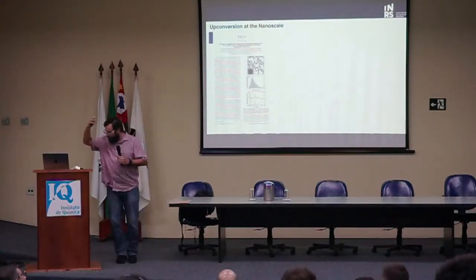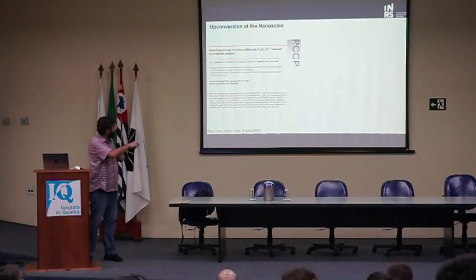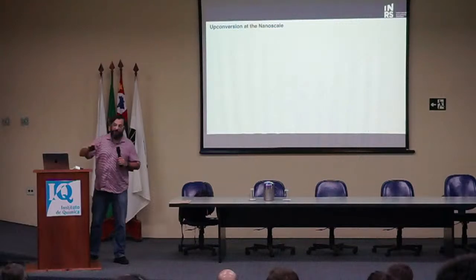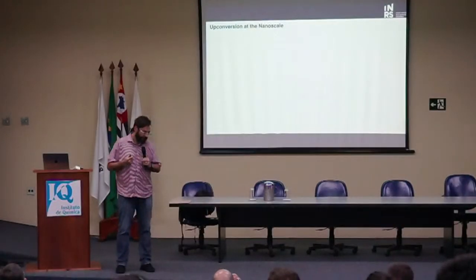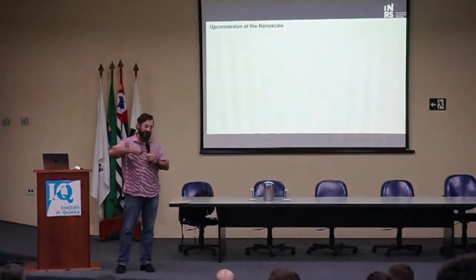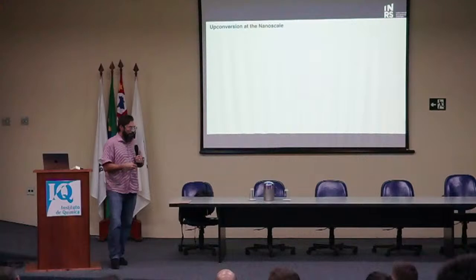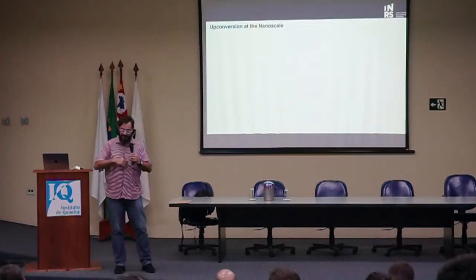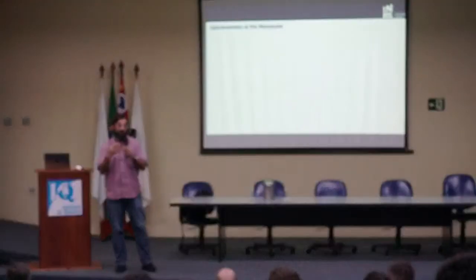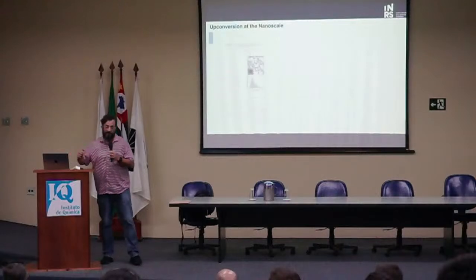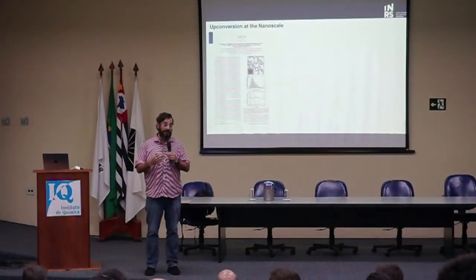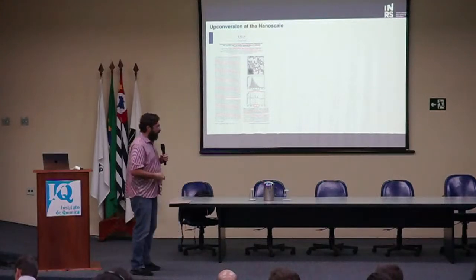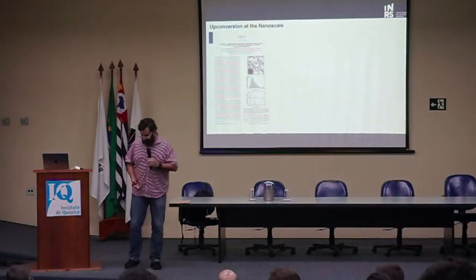That first paper was on sesquioxides, on yttrium oxide. And at some point during my PhD, we got the idea that these materials could potentially be used in biological applications because we're exciting them in near-infrared light, and near-infrared light has tissue penetration capabilities, as I'll show. So maybe there's some potential there in biology and biosensors. But the problem is that the materials we were working with were made with a very crude combustion process. So basically, you mix the oxides in glycerin, and then you heat it, and it explodes, and you get these nanocrystallites, which was cool for fundamental studies, but for practical application, wasn't cool. And of course, we wanted to move to fluorides because of the low phonon energies and so forth. So after a few years, we published this paper where we published the synthesis of these materials.